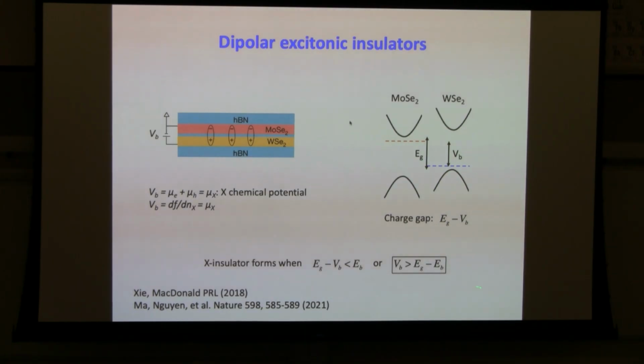Okay, yeah, and well, put it another way, when the VB is tuned to be larger than the exciton energy, which is Eg minus Eb, you can spontaneously populate a fluid of excitons. So by looking at this picture, you can see that the VB is equal to the sum of the electron and the hole chemical potential, and that's just equal to the exciton chemical potential. So it's very nice in this setting, the exciton chemical potential is just very easily tuned by this bias voltage.